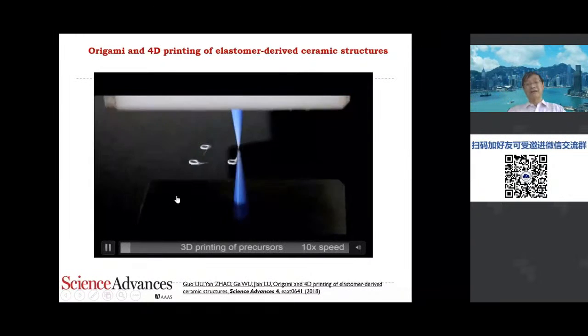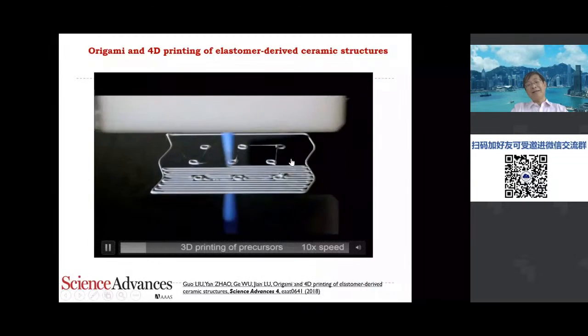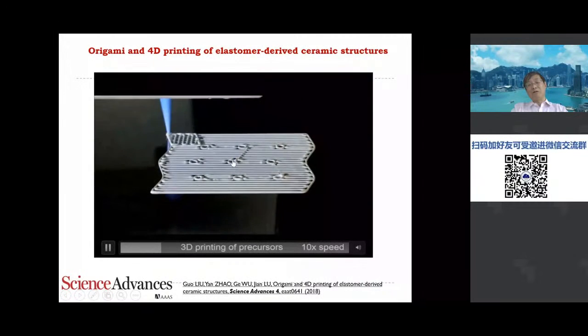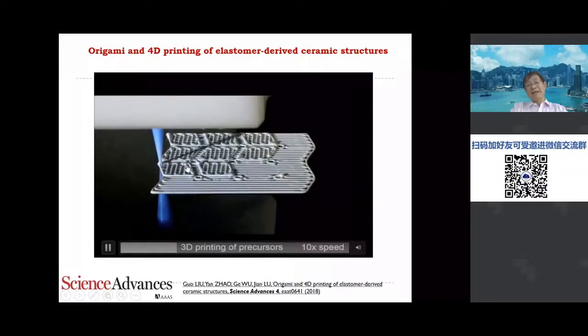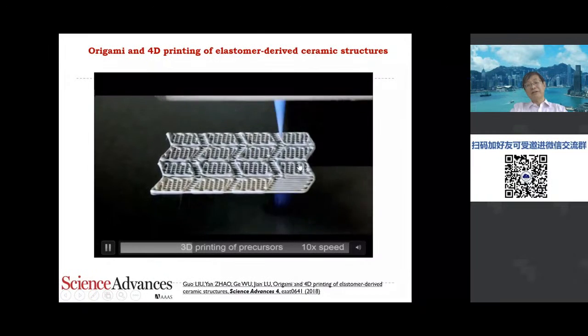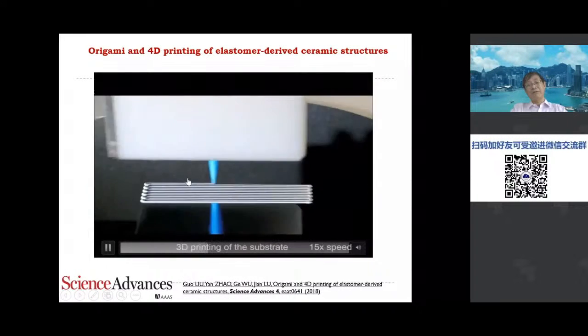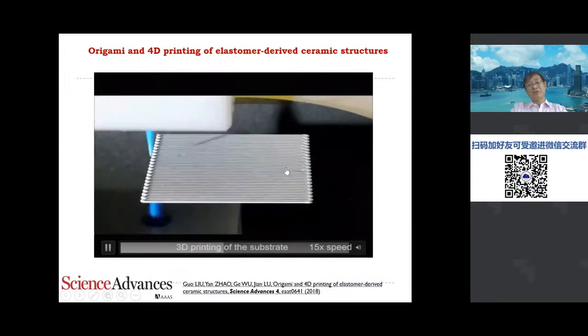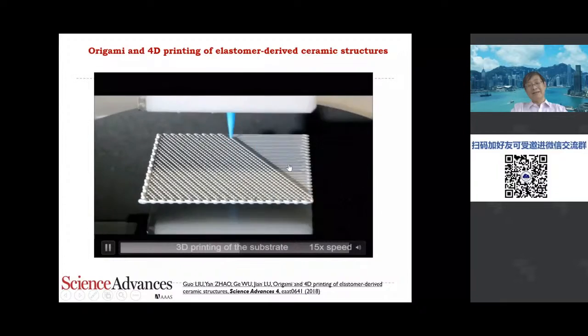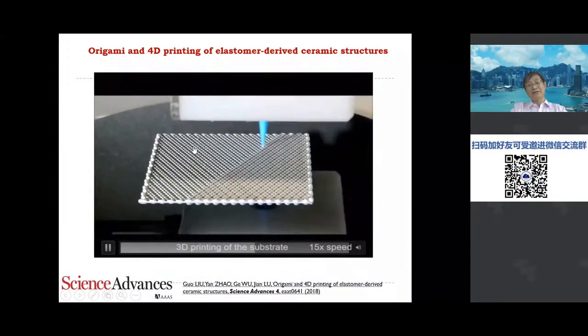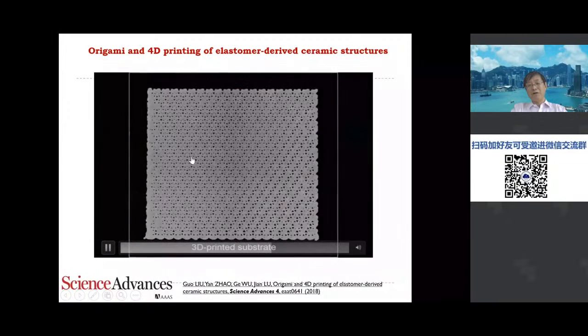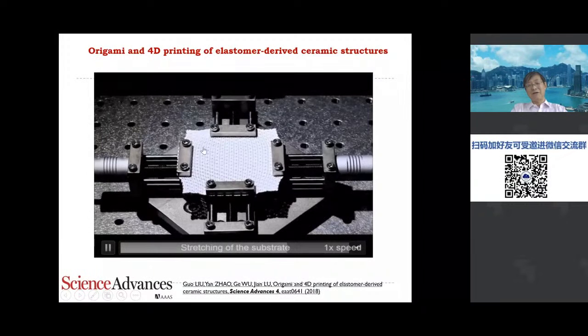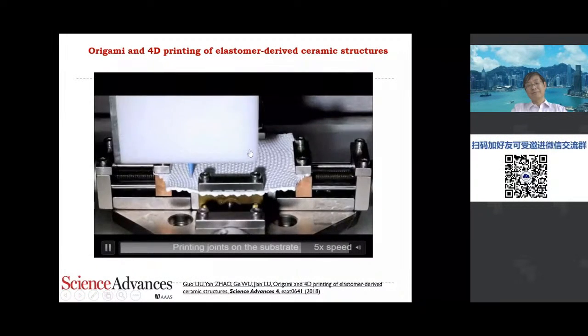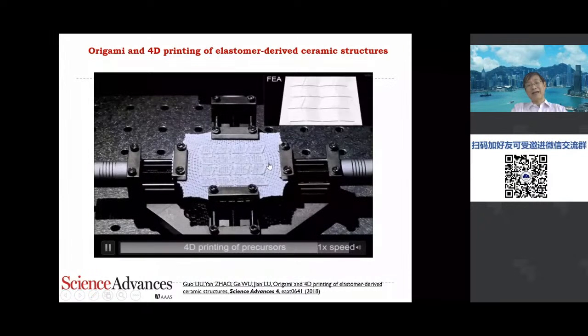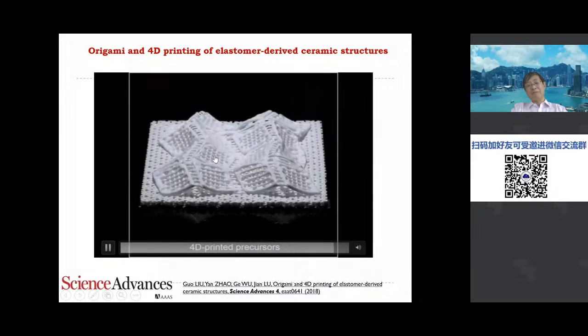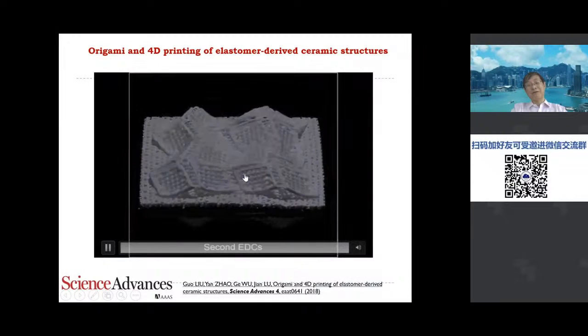So how do we obtain the complex shape? Basically, at design level, we design some articulation points. Then we print a two-layer structure, which is directly printed on top of a substrate. This substrate will be deformed, okay? You will see, we deform this substrate with programmable deformation. Then we print on top of this. After the printing, we can relax the deformation and then obtain a very complex shape of ceramics.